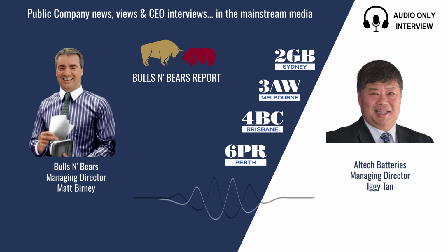All right, so you say you've cracked the silicon code. How does your technology work? What we do is we coat it with a very thin layer of high-purity alumina, and essentially that keeps the expansion from creating problems, and it also resolves the first cycle loss. And we announced that a couple of years ago. We can produce batteries at 30% higher energy capacity.